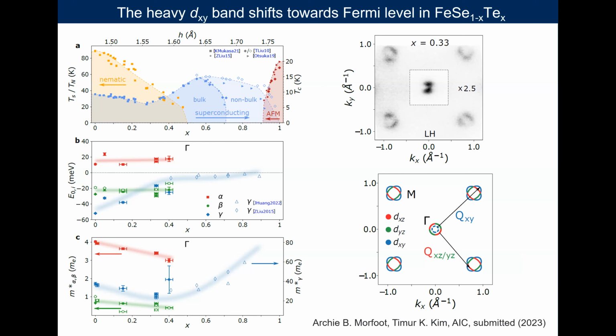And if we look at the correlation with the presence of the second superconducting gap, we notice that the dxy band is coming towards the Fermi level more or less when this superconducting dome starts to increase. So it's likely that we have a new pairing channel now given by the dxy band, which potentially helps to boost the second superconducting dome in iron, selenium, tellurium.